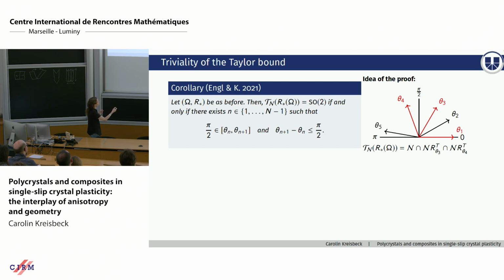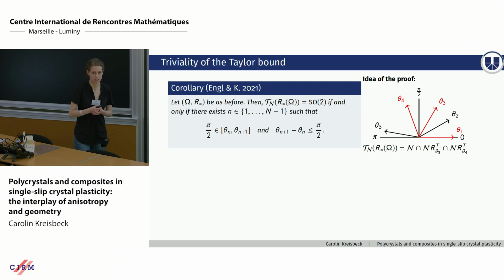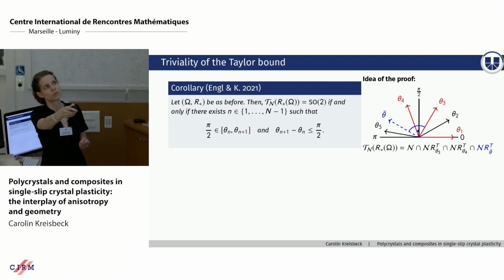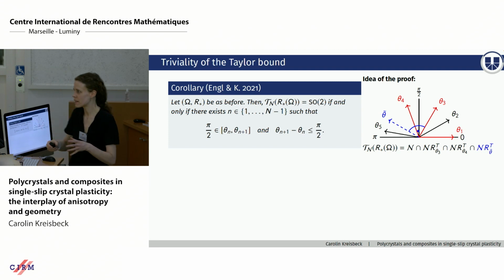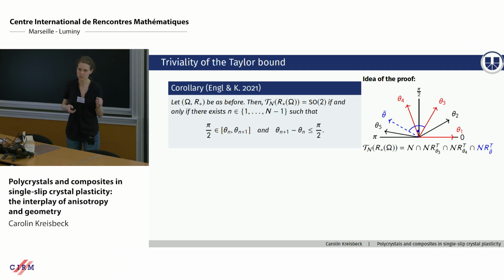So I'll show you. If we have a polycrystal with these 5 directions, we know from the previous observation that this Taylor bound corresponds to the intersection of the 3 red ones. Now we add another one, the blue one, theta tilde, from which we know that it doesn't change anything if we add this intersection to our Taylor bound, because theta tilde is further away from pi over 2 than theta 4. But now we see that these 2 here, the one associated to theta 3 and theta tilde, their intersection only contains rotations because they have a 90-degree angle, and so the Taylor bound needs to be trivial.